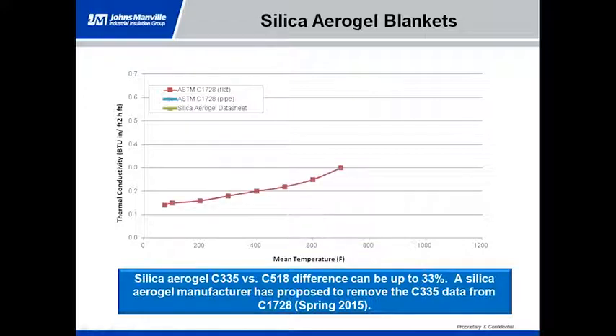Now, one example that we have is silica aerogel blankets. This is kind of unique in the ASTM standard specification in that you have both flat and round values in the same standard. The closest thing that we had on the prior example was mineral wool, where we had a different standard specification for boards and a different one for pipe. With silica aerogel, they just incorporated those two thermal curves into one standard specification. So this is the line that you're going to see for flat data. There's another line, of course, for the pipe data, and the product has to be at or below that line as well when tested in a pipe configuration.